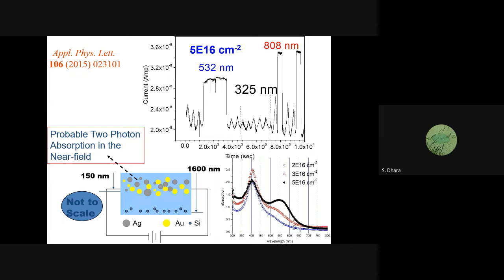This is a material which is made not by even annealing. We have annealed it by another ion. The bottom is the silicon ion. You can anneal metal nanoparticles by another ion which is not miscible with that system. Gold and silicon are not miscible, so very high energy silicon is used to make these gold or silver nanoparticles bigger. During their impact, local thermal conditions can help these nanoparticles grow.